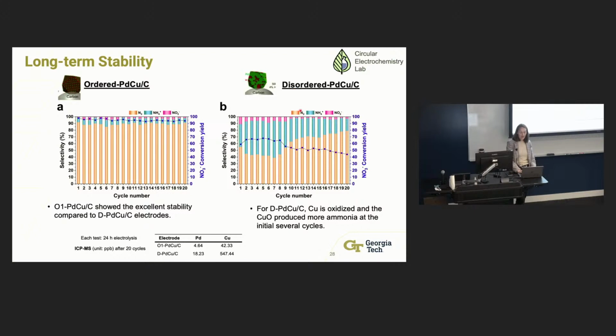This specific disordered alloy seemed to show really different products. And this actually could mean that it is thermodynamically trying to move to this stable form. We can see we're starting to get more nitrogen and less ammonia with time. So it seems like this one is trying to move towards this catalyst. And that's okay, but if you're trying to make a product, you want the same product from the start, and so the ordered is ideal. The only downside was that the ordered catalyst selected towards nitrogen and not ammonia.